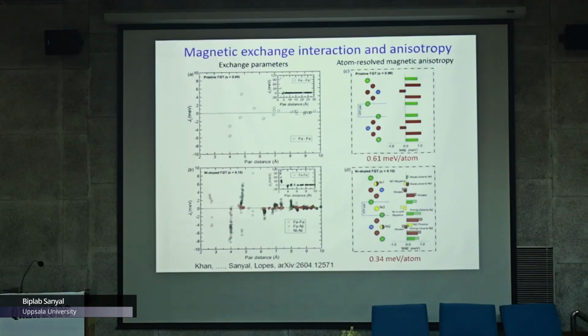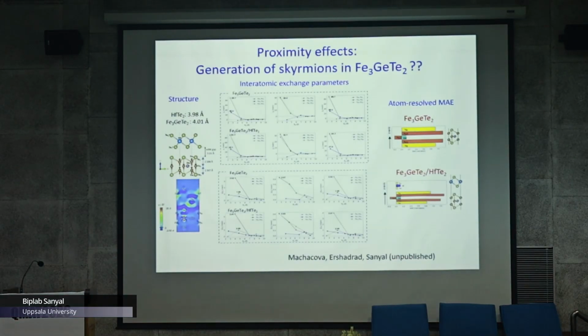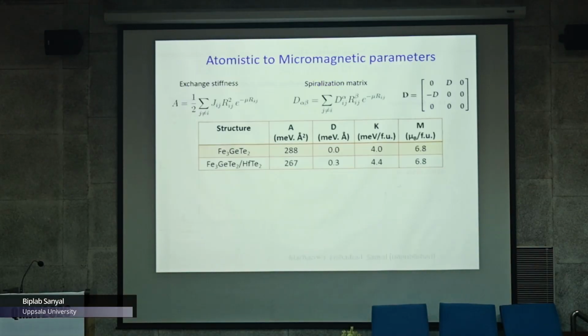So this is good. Then I come to the proximity effect. Now we have the same system, the iron 3 germanium telluride system. So can we generate some skyrmions here? First of all, I already told you that this is a centrosymmetric system, so we cannot expect to see them in a pure system like that. So we thought, okay, let's take a material like hafnium ditelluride, which is also a synthesized two-dimensional material. It has a high spin-orbit coupling, and let's see whether the proximity with the iron 3 germanium telluride can make any difference, can do something extraordinary.